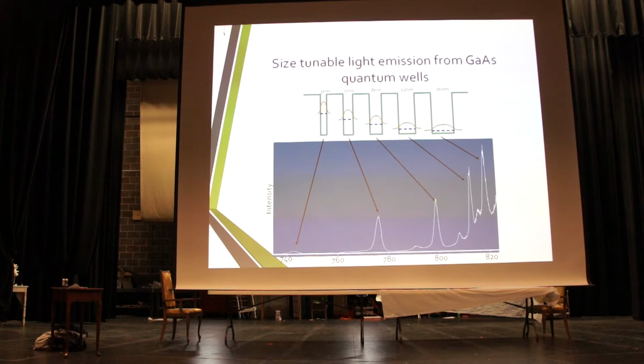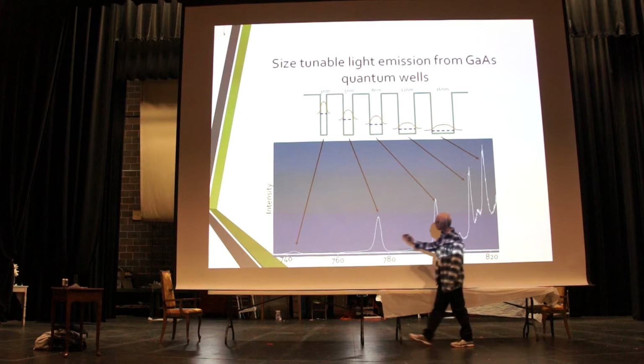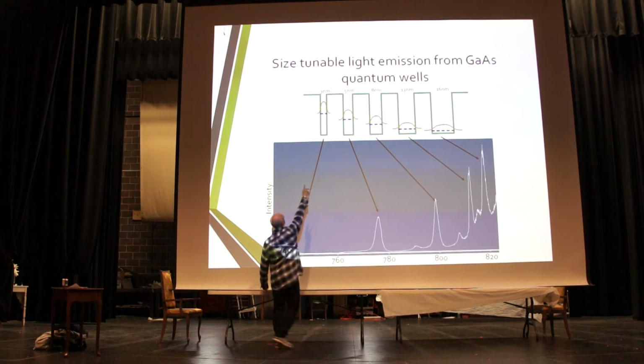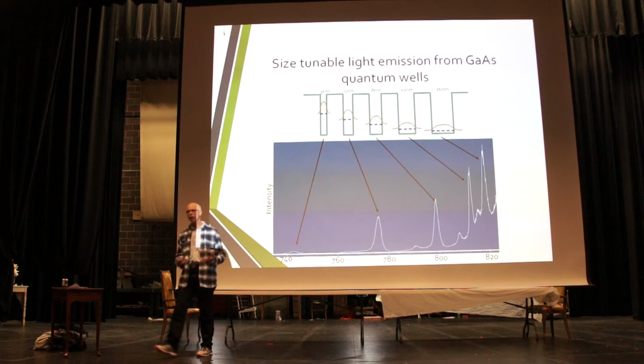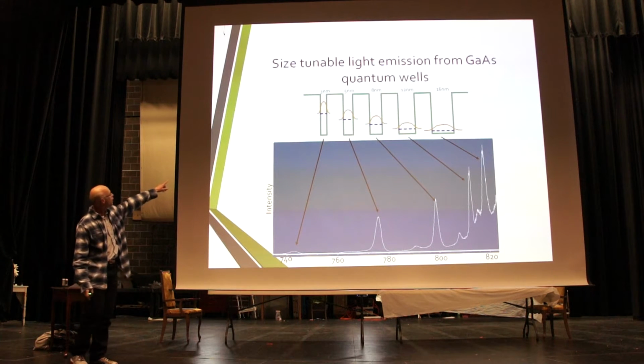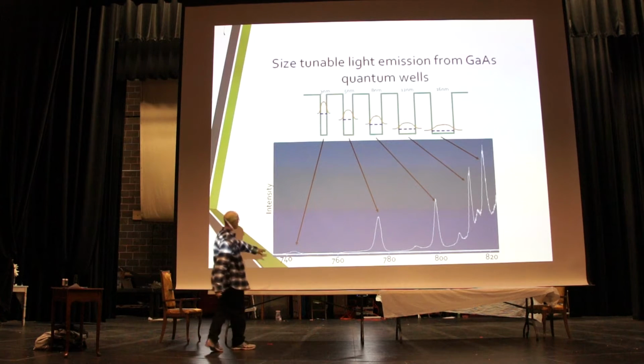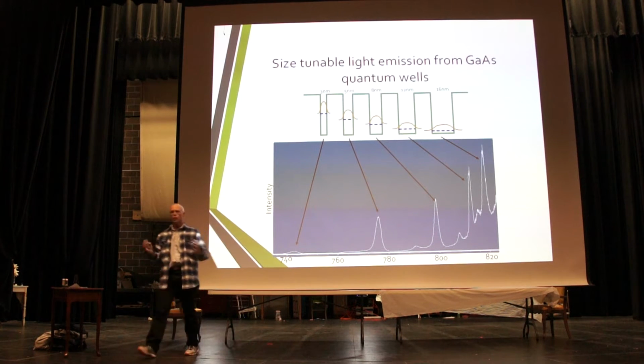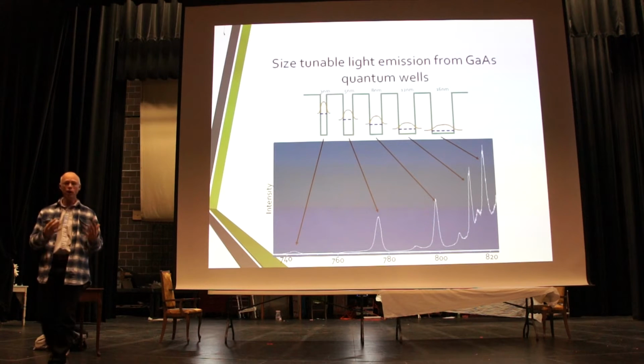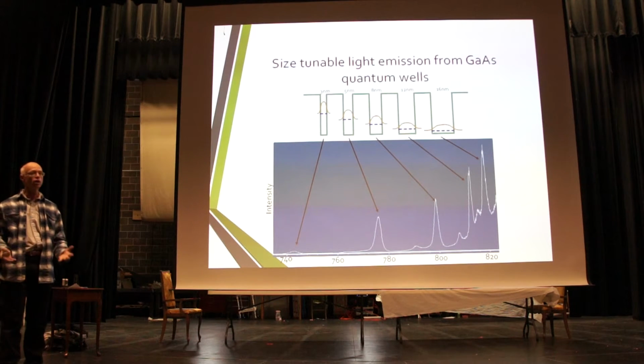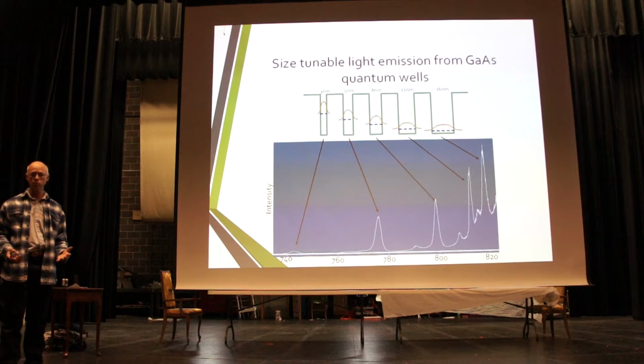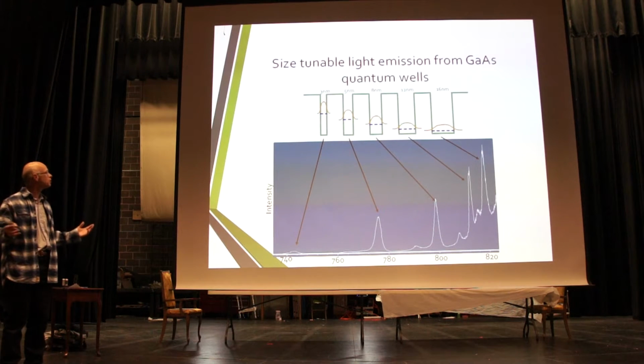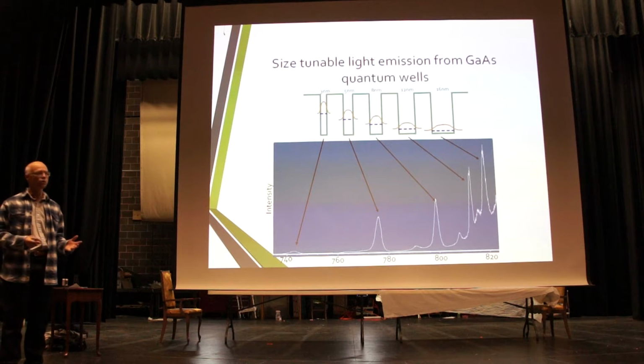This is a sample grown like that, and this is the emission spectrum, which actually Connor measured. You can see you have multiple peaks in the emission spectrum, and each one of these peaks can be associated with one of those wells. The well that is the narrowest gives the shortest wavelength, which is the highest energy. So we can use size to tune the energy of the material, to change the color that it emits, which is pretty cool. That means we don't have to develop a new material. We can just quantum confine the material that we've got.